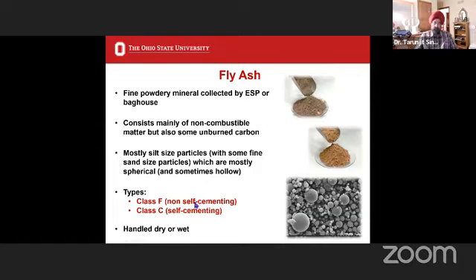So to harden up class F fly ash, I will not only need to add water, but I will also need to add some calcium oxide. On the other hand, class C fly ash does have a significant amount of calcium oxide. All it needs is water and it can set up. Now, coming to this non-self-cementing class F fly ash, when you add water, it will not harden up. It has friction, but not cohesion. Class F fly ash is very, very interesting.